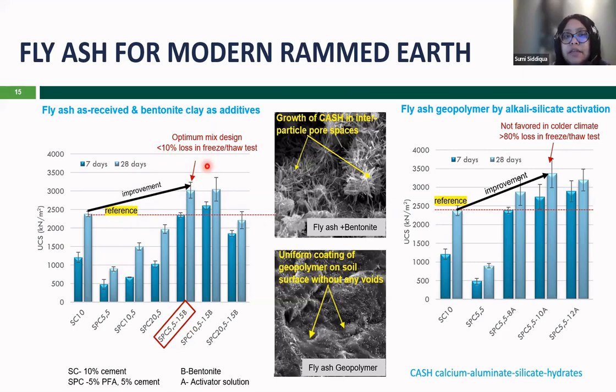We saw the 10% loss in the freeze-thaw testing. When we run the freeze-thaw testing, we have seen less than 10% loss of the strength. So that's why it is identified as our optimum for these given conditions.